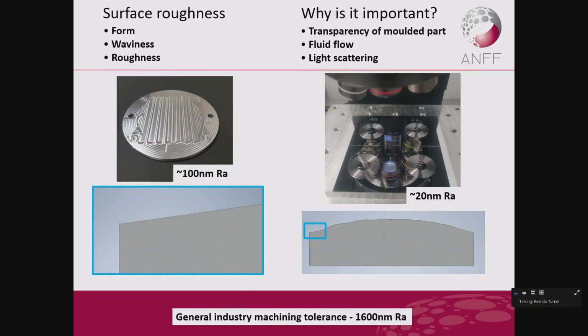So I've talked a little bit about surface roughness and the monocrystal diamond tools, and this is the difference between them really. We've got 100 nanometers, which is actually pretty good, because in general industry, the general tolerance for surface roughness would be 1600 nanometers. So it's still very good, but it looks rough. Here we've used a monocrystal diamond tool to make this mold, and you can see the difference in the brightness of the material because of the sharpness and the hardness of the diamond.